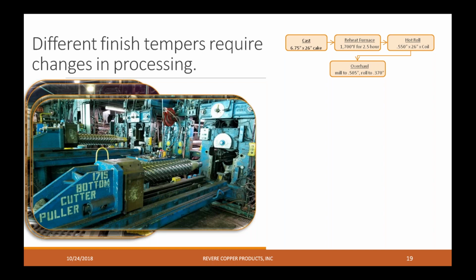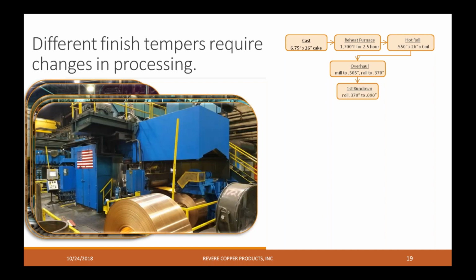But then our next step, this is where the cold work starts. We roll it to 0.370. So we take that metal and we roll it down further, depending on the order and the final gauge. And I'm running through an example here. I'll show you what we're headed to in a minute. So the next step is we continue to cold work it from 0.370 down to 0.090. So that's a 75% reduction. That's a lot of cold work. So this metal is going to be extremely hard at this point.